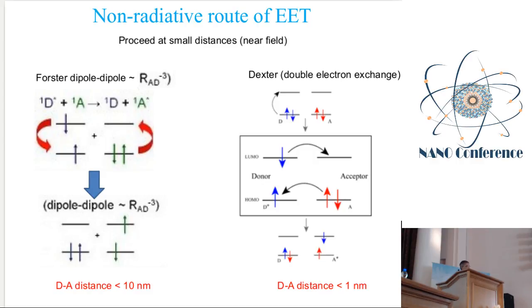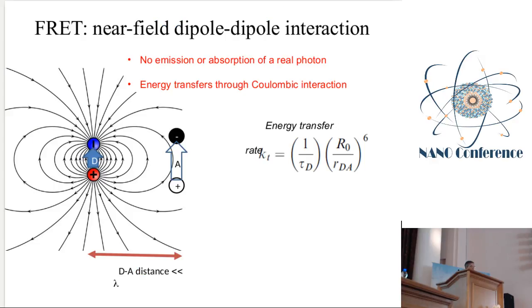What is more important for Forster resonance energy transfer is that in this case we do not have transfer of a real photon. In this process, when the donor dipole is excited, it immediately induces excitation of the acceptor. So this process is very fast. It proceeds during a few picoseconds or even less. And the efficiency or the energy transfer rate can be described by this expression. So the rate is inversely proportional to the distance to the 6th power.